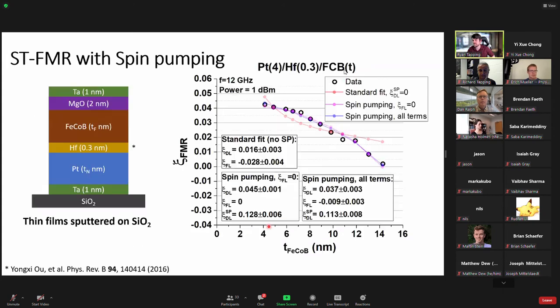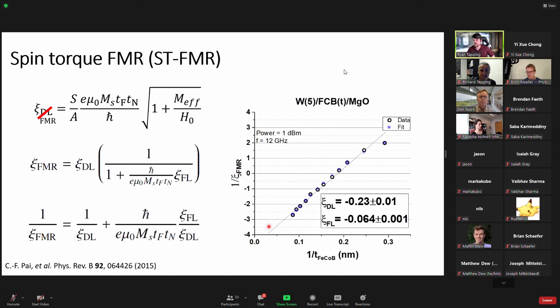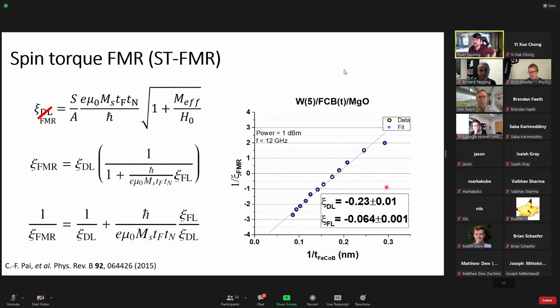There's something related: when I measured the sample I said should be linear, you'll see some non-linearity in the data, but my fit matches the data points very nicely. I've accounted for another effect — even across the wafer, thicknesses vary a little bit due to sputtering. So deviations off the line are actually expected based on thicknesses measured from calibrating the entire wafer. Even on one wafer, the thicknesses can vary.